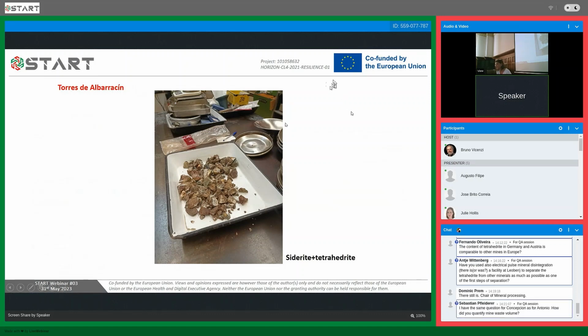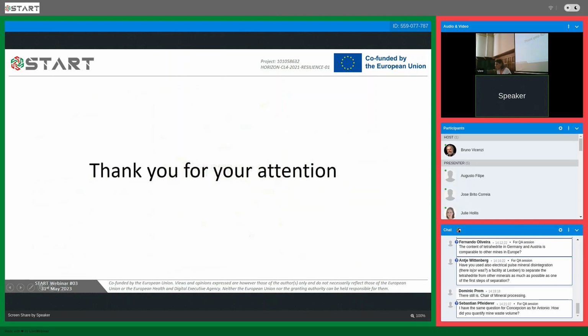According to their mineralogical composition, we have to try to carry out mineralogical separation tests. For the sample from Torres de Albarracín, the most favorable so far, we have passed them through the Franz magnetic separator, so we have been able to discard the sulfide sediments. Then we attack them with acid to remove impurities. In the Serrecilla case, the mineralogical separation is still under discussion because the grain size is very small, and we have many problems deciding which method is better to use. And that is all the work carried out so far on the different tetrahedrite mines in Spain. Thank you for your attention.